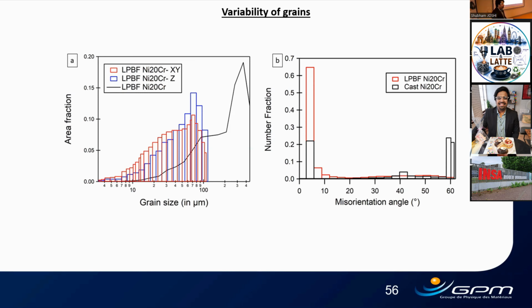To be sure I understand it, that means that the grain size you use in your modeling is an average between the two planes? Yes. It's an average between two planes. It is a crude, again, I think, method when it comes to grain size, because the aspect ratio will increase certainly with increase in volumetric energy density. So again, as I said, there is a variability in terms of microstructure, and certainly it will influence the model. But for the average, we have tried to show.